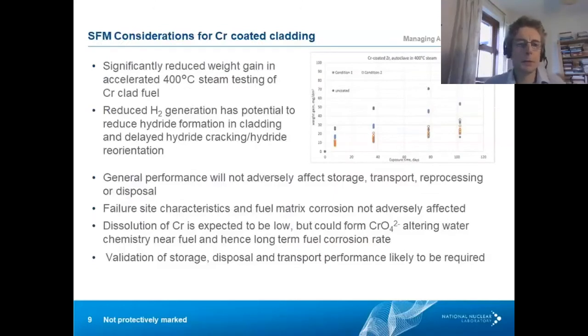So in terms of thinking about their impact on the back end, chromium coating significantly reduces weight gain during steam testing. So hydrogen production is also reduced in normal operations, and therefore the risk of hydride formation or reorientation during subsequent storage is also much reduced. And in general, we expect that the performance will not be adversely affected, whether that's in storage, transport, reprocessing, or disposal. The failure site characteristics and matrix corrosion are not expected to be adversely affected.